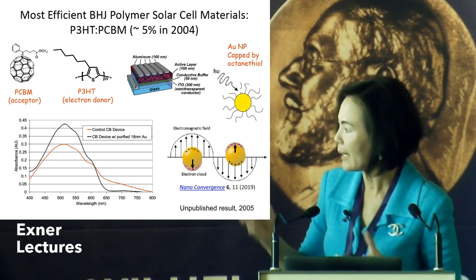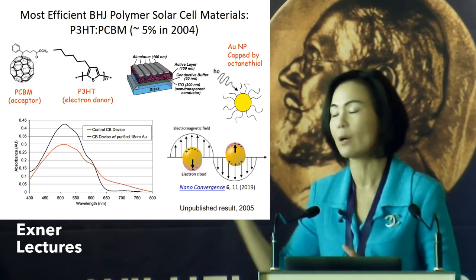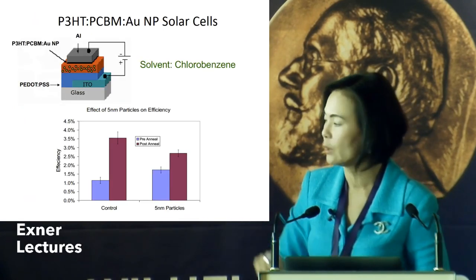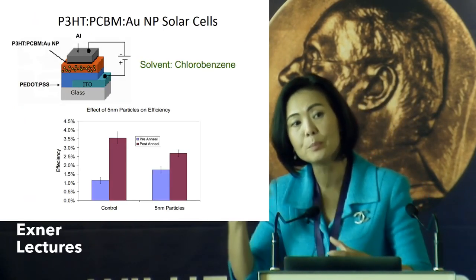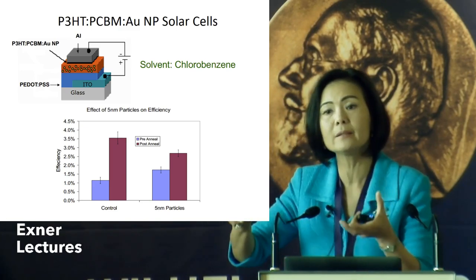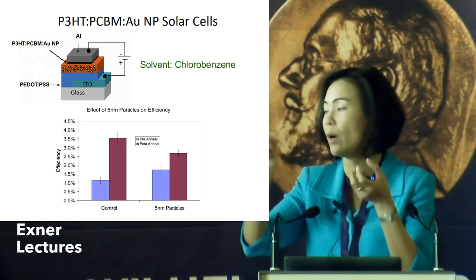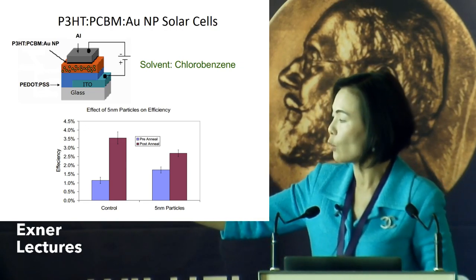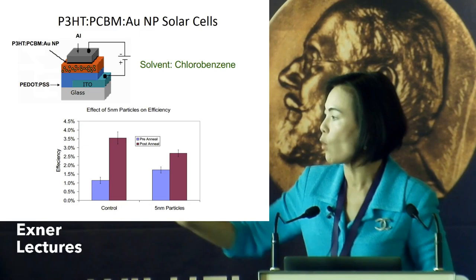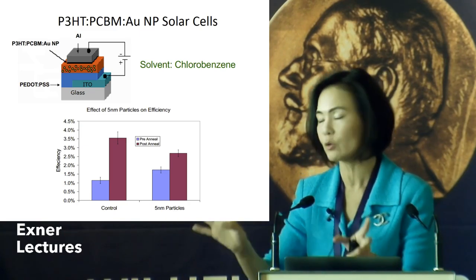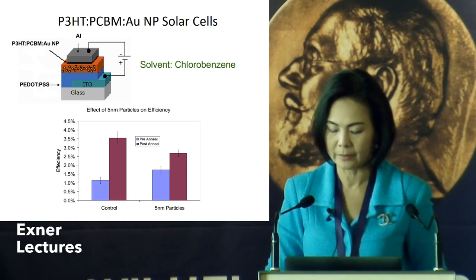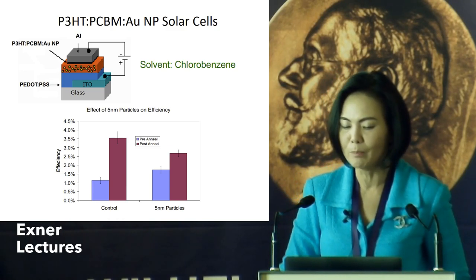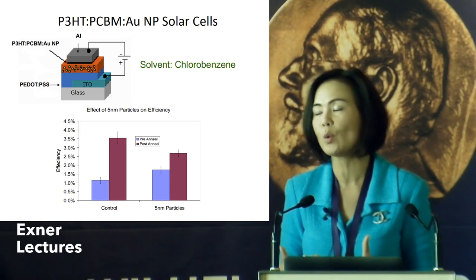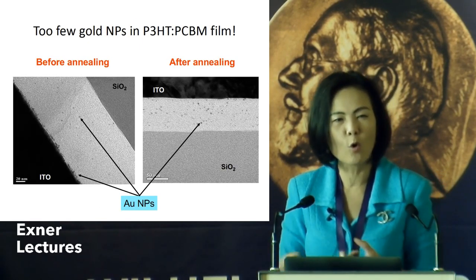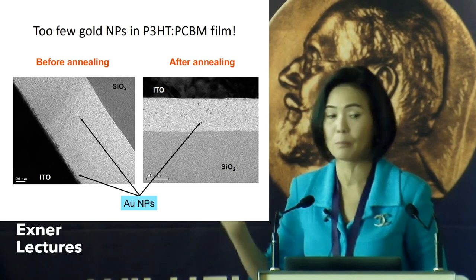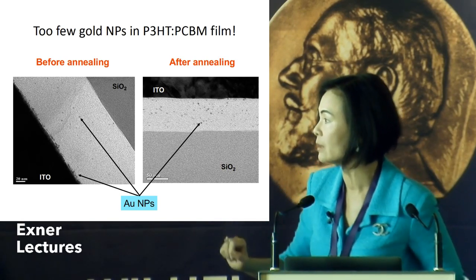And so when we blended it in and made the solar cell, on the left is the control without the gold nanoparticle. Normally, to improve the device performance, people have to take the solar cell and heat it up, thermal anneal it. But on the right, we added only a small amount of gold nanoparticle, as cast without thermal annealing, and we can have better device performance. So then we were about to submit the paper, but we decided to ask the question, what exactly is the gold nanoparticle density in our active layer that gives rise to such improvement in the device performance.